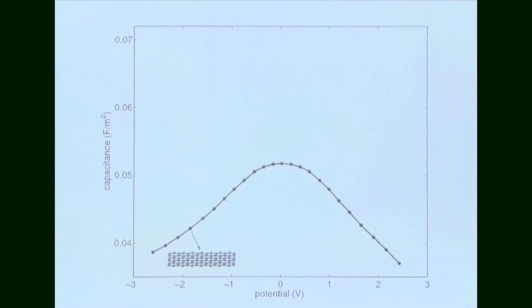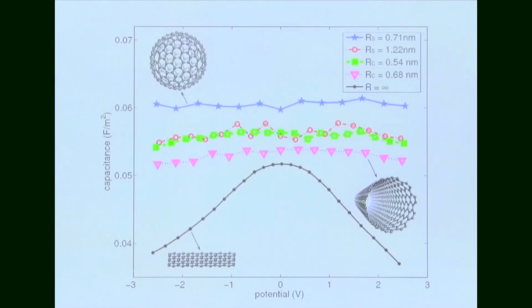The differential capacitance as a function of potential is shown here. We can see that there is a bell-shaped capacitance versus potential curve for planar electrode, which agrees with previous studies. For the supercapacitors based on carbon nanotubes and carbon onions, the differential capacitance depends weakly on the electrode potential, and this feature becomes more pronounced with the decrease of electrode size. The capacitance for both carbon nanotubes and carbon onions is higher than that near planar graphene.